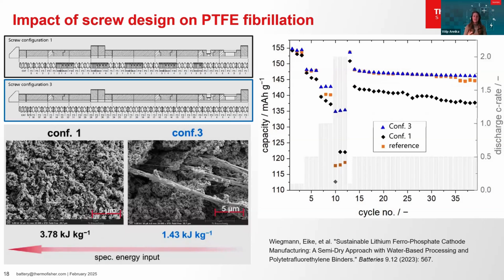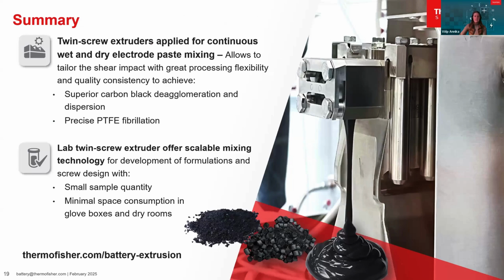This study suggests that the PTFE fibrils in the strongly sheared sample isolate the conductive pathways, leading to inactivation of the LFP. This highlights the importance of tailoring the screw design to provide the right energy input for the specific PTFE grade. And this brings us to the summary of the presentation on twin screw mixing for processing dry electrodes. I would like to highlight the following points.